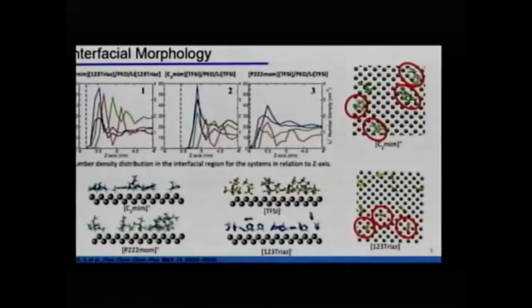We have the first layer that contains the anion, cation, and PEO, and same here. So here and here, we can see some indications of the formation of the passive layer that the ionic liquids can create on the metal surface. But when we compare 2 and 3, so imidazolium TFSI and phosphonium TFSI, we can see that when we change the cation, we change a lot the distribution of the particles in the box and close to the surface. Here in blue, this is the cation peak. So we see here a sharper peak, very high density. But when we look here, we see a broader distribution and a smaller intensity.